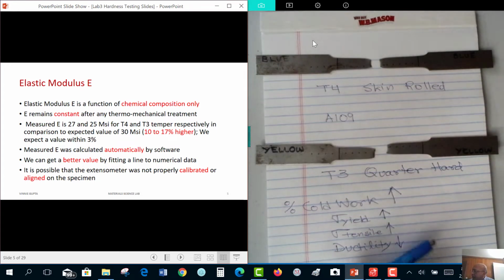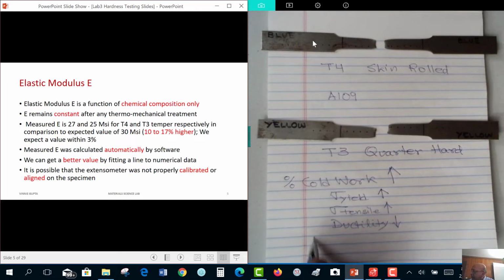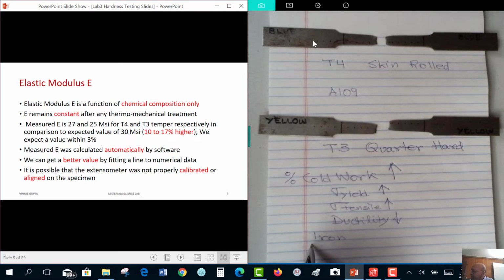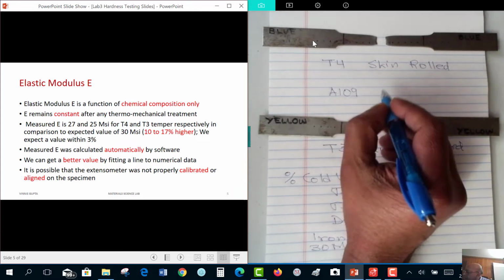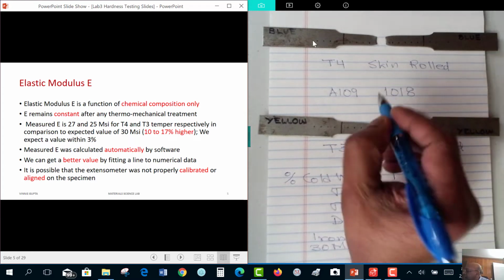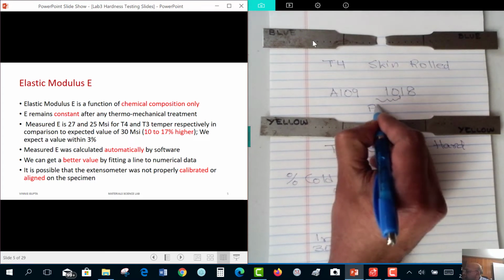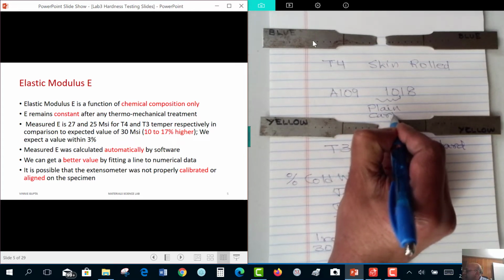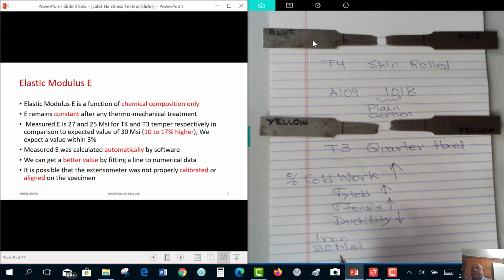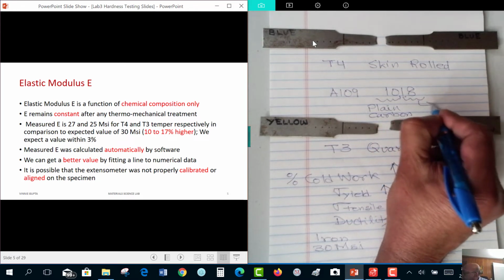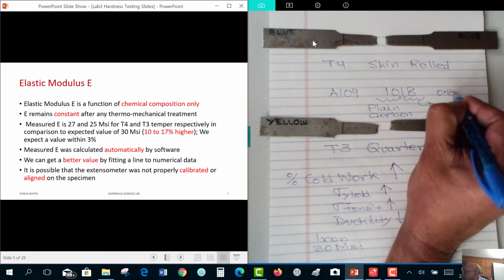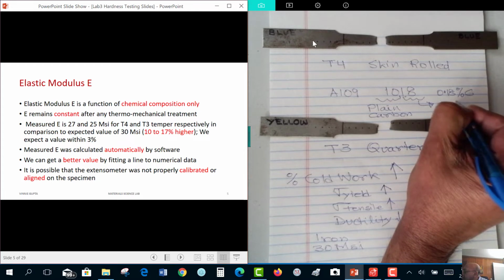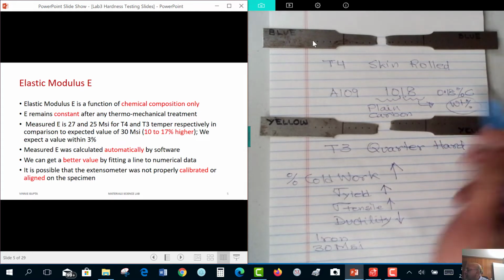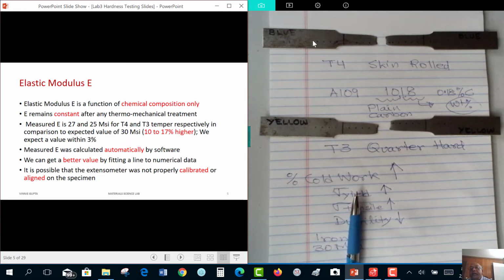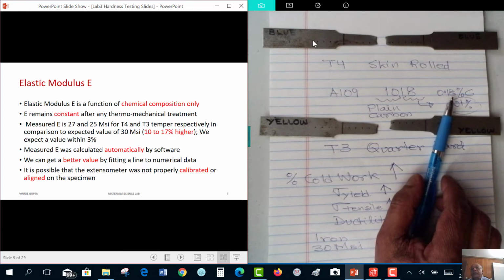In fact, pure iron has the same elastic modulus, 30 million psi. So let's talk about this 1018 steel. What does 1018 mean? The first two digits mean this is plain carbon, that means carbon is the only alloying element in iron. And the next two digits mean that the amount of carbon in the steel is 0.18%, and this is weight percent. We always talk about weight percent unless otherwise specified in material science. So this is a very tiny amount of carbon.